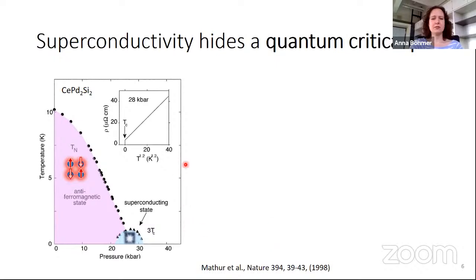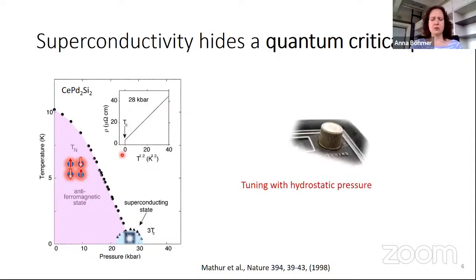And this is one of the first cases where such behavior was observed. What we see here is an antiferromagnet, cerium palladium 2 silicon 2. And if you apply pressure to it, physical pressure, then this transition temperature gets suppressed, just as we said. And we see a dome of a new phase. And this phase is a superconducting phase. This is the electrical resistance. It goes to 0. So here we're tuning with hydrostatic pressure.